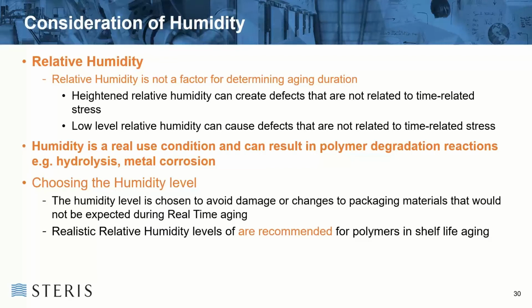So, for example, the box falling apart would be one of those, or the box softening, and the whole package collapsing when there's a load put on it. If you go the opposite way, where you're putting a low level of humidity in the box, which some customers do, they try and go down between 5 and 11%, which you can do when you extrapolate the formulas or the graphs in ASTM F1980 down. But the problem here is that there are very few places on Earth that you're going to get a 5% relative humidity.